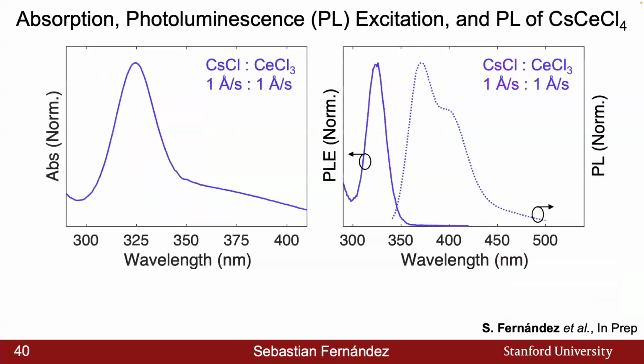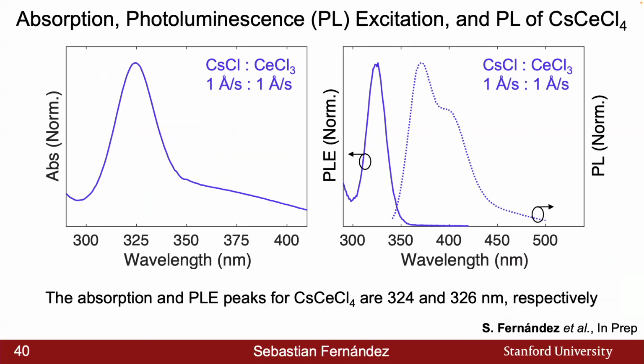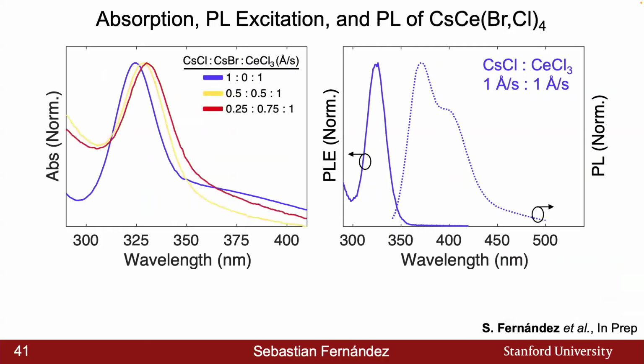So now looking at the optical properties of these perovskites, we can look at characterizing the absorption and the photoluminescence excitation of these thin films. And accordingly, as was shown in the perovskite nanoplatelet section, there's good adherence between the absorption and PLE peaks centered at around 325 nanometers. And additionally, now we can introduce cesium bromide and do this tri-source thermal evaporation, in which let's see what happens if we use halide engineering. Can we affect the optical properties of these thin films?